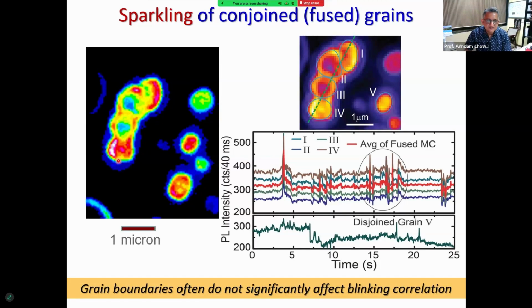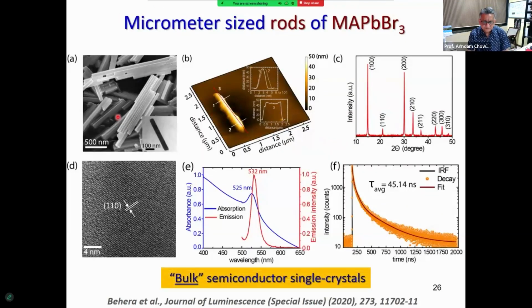And you will show this kind of sparkling behavior intermittently. There's a huge burst of photons coming out. If you look at the grains 1, 2, 3, and 4, there are huge areas that I'm talking about, and you can see they have very, very highly correlated emission coming out. These fluctuations are correlated. As compared to 5, over here on the lower right corner of the movie, you will see that the behavior is completely different from that of the fused grain systems.